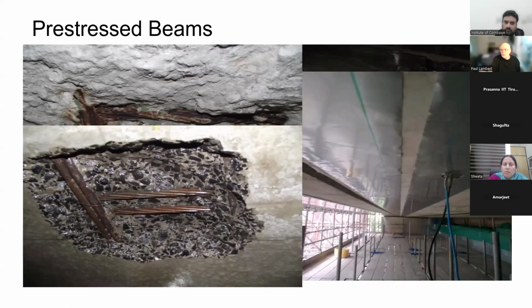So this is a very early trial. We're going for about 20 years now, and it has been widened out. You can see the connection there. The whole of this, by the way, has been coated with a cementitious coating to hide the zinc, match it in better, and also protect it from its self-corrosion. Perfectly capable of using it. Sounds low tech, but when you think about it, it's real cutting edge.